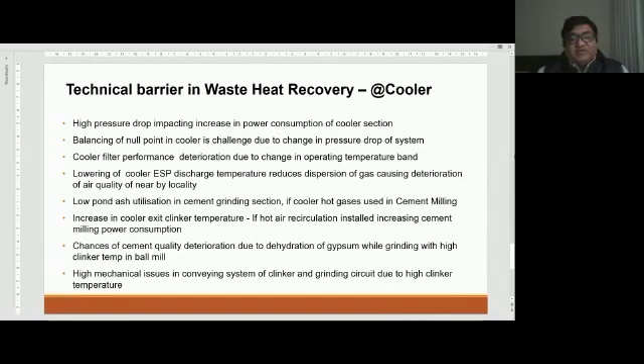before you put this in, because when you have the high temperature, the clinker goes to your cement grinding, your grinding power increases, and your gypsum dehydration process changes, which needs a lot of water to be sprayed in the mills, especially the ball mill or the VRM, to maintain the bed. So this is another side of the considerations we take for the technical barriers. We have to find the optimum point where you maintain your cement quality, cement operation, clean operation, as well as generating the power.